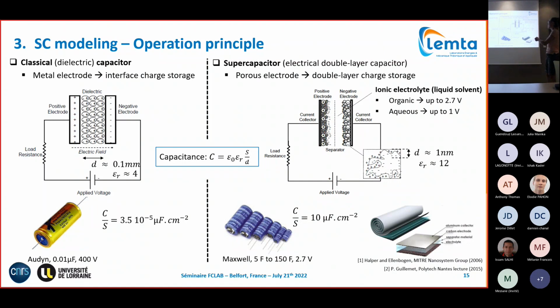So primarily it's the case of capacitive charge storage. It's electrical double layer capacitors, which store charge in the form of an electrical double layer, and this means you have a significantly higher charge storage surface area than in a classical capacitor, and a much lower charge separation distance, on the order of nanometers compared to the order of millimeters in a classical capacitor. This means you have significantly higher specific capacitances in supercapacitors, on the order of six orders of magnitude higher, more or less, than classical capacitors.